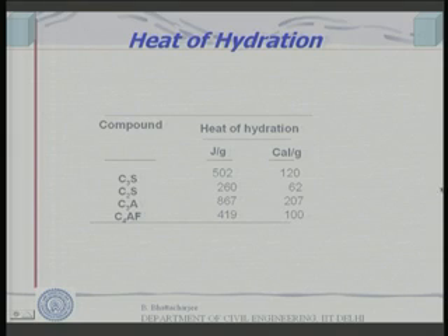So, as we can presumably understand, C3A will react faster than any other, and C2S will react at a slower rate because it generates less energy. It is not an explosion, but it generates a lot of energy, so it is instantaneous, whereas where the heat of hydration or the reaction heat is relatively less, it will be a slow process. So, this reacts immediately, maybe the next thing to react is this, and lastly this reacts. So, it takes a long time for the C2S reaction to be complete. Right. So, this is the heat of hydration of pure compounds.